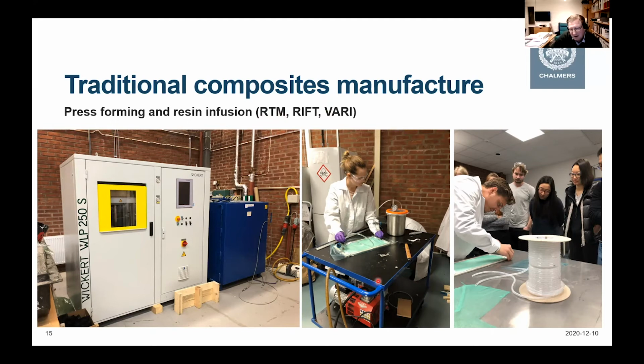Then we can get a very highly organized, high performance composite with 65% volume fraction of fibers. This is showing the VARI or RIFT type of technique, where we have a pump sucking vacuum, and then actually we have a pot. This is also evacuated, and we have the resin in there, and we suck in the resin, and the resin front is moving across the tool, and so we have dry fibers in this region, which are dry and are wetted by the monomer solution, and then we put this into an oven and cure it.